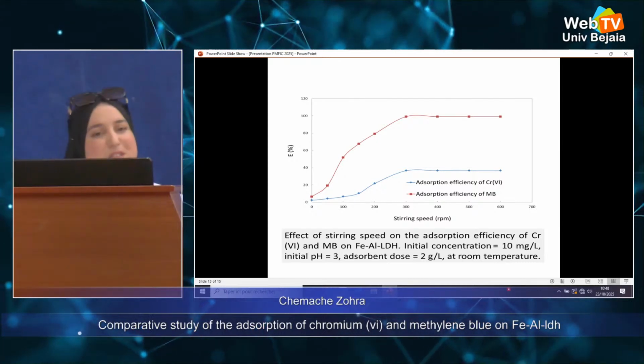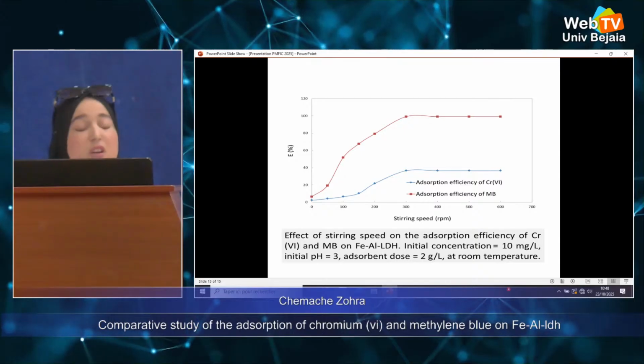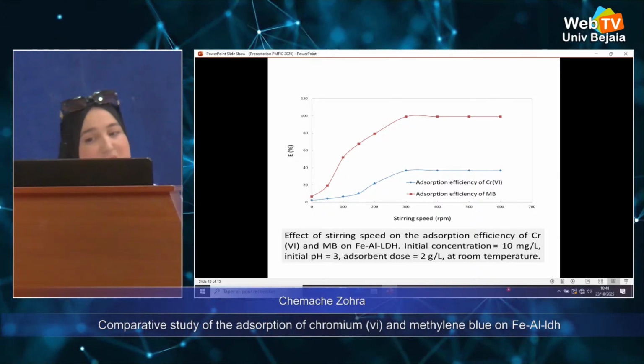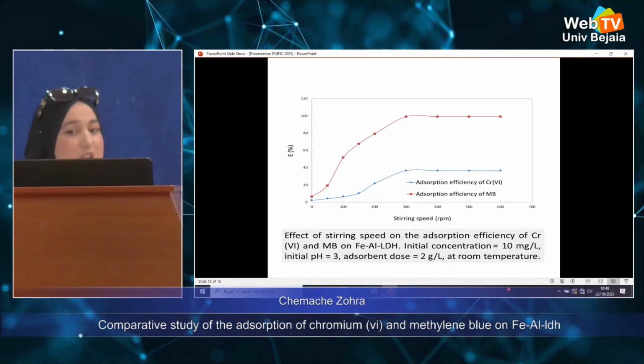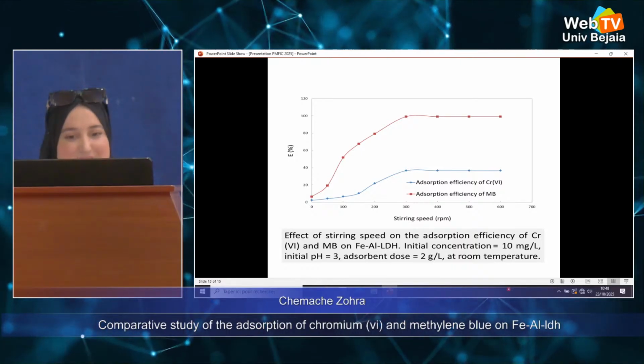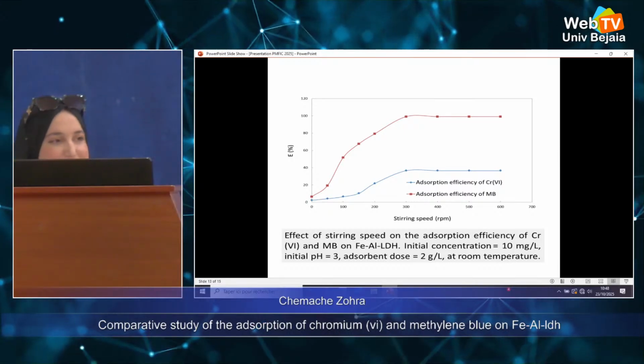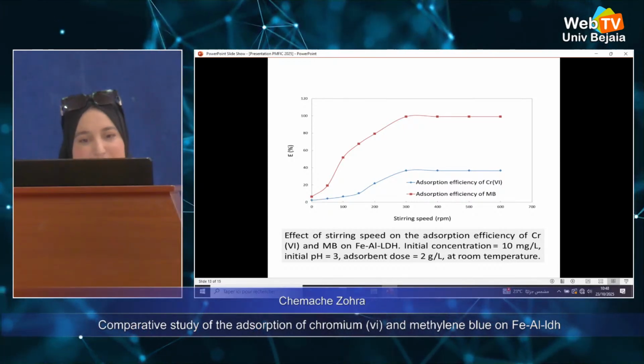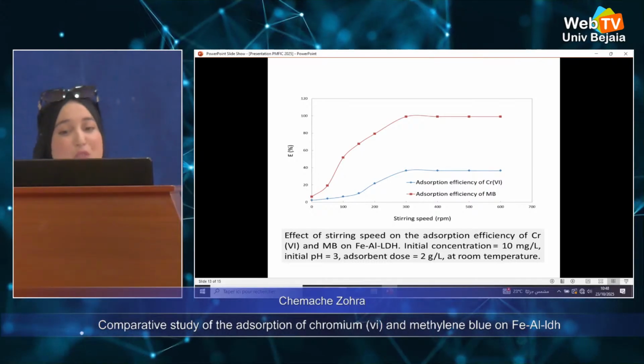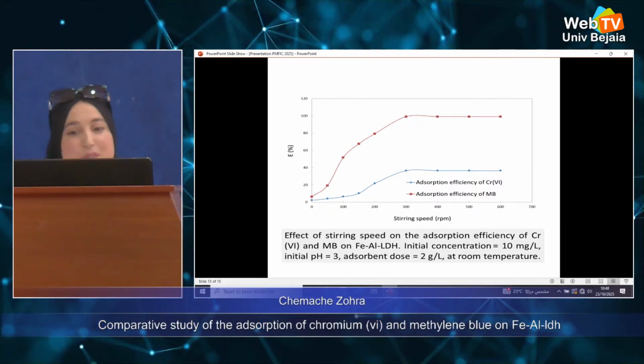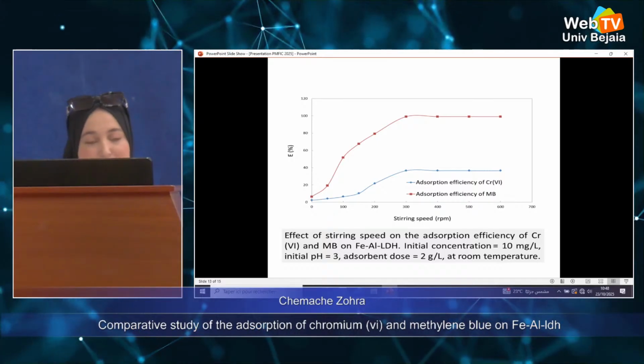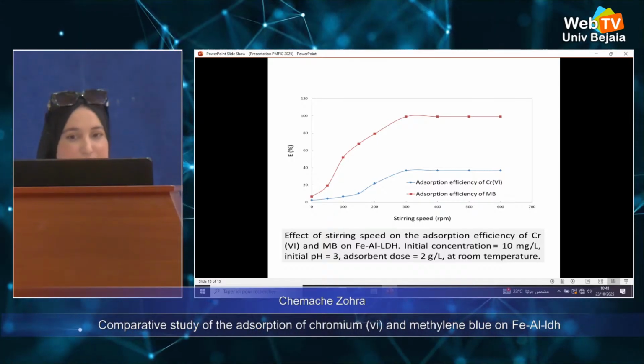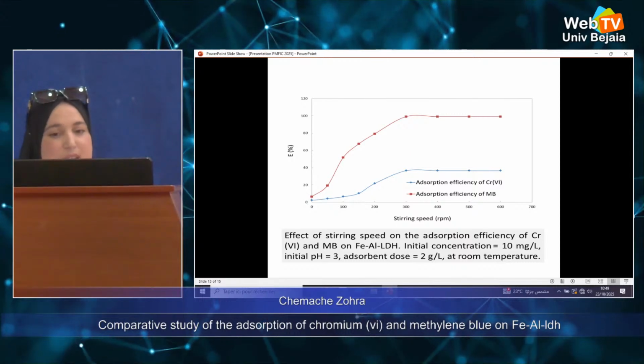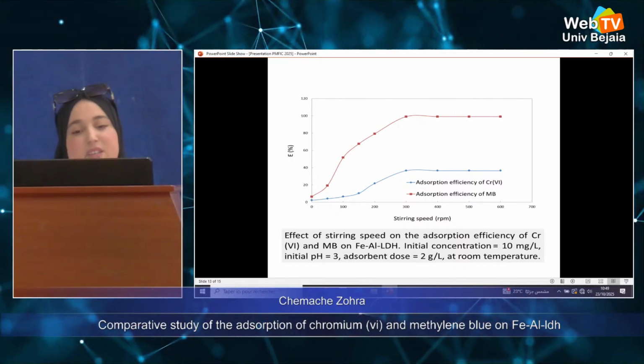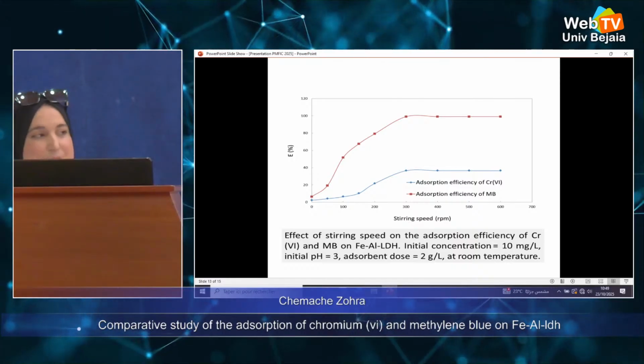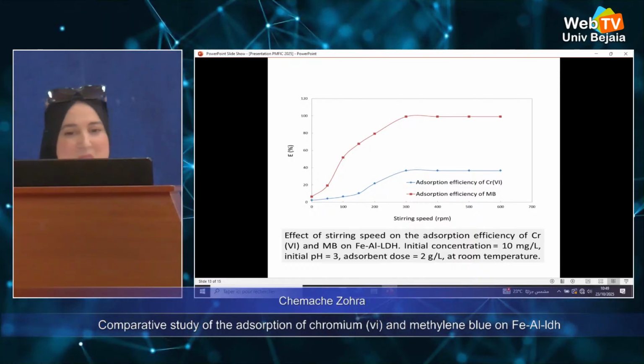In order to determine the optimal stirring speed on the adsorption efficiency of chromium hexavalent and methylene blue on iron aluminium LDH, the adsorption tests were conducted over a range of 0 to 600 RPM. The results shown in this figure reveal that 300 RPM is the optimal stirring speed for both systems.